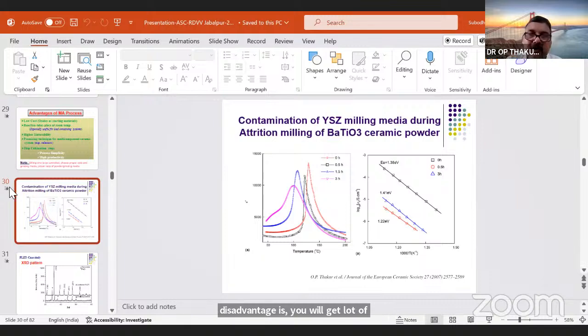contamination from the grinding media. So what I did is I took barium titanate as a case study. Then I did the grinding for different hours: 0 hours, half an hour, 1.5 hours, 3 hours. So you can find the shift in the dielectric constant peak for 3 hours. That means this peak shifting, because for pure barium titanate, the transition temperature is around 120 degrees centigrade. But if you induce contamination by longer time ball milling, that means the zirconia is coming from your grinding media, because I have used zirconia grinding balls. So that zirconia diffused into the barium titanate, and which has shifted my TC to lower temperature.